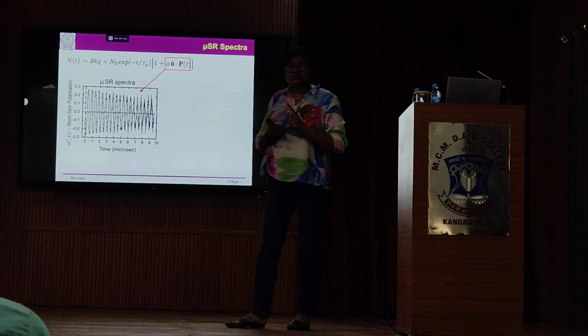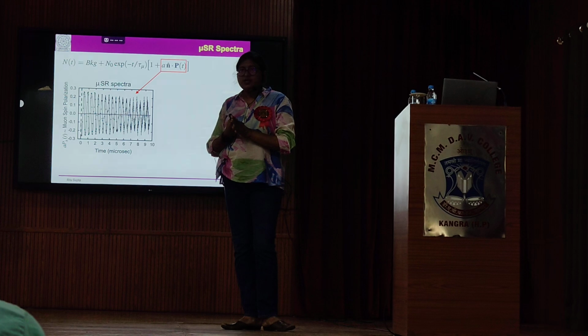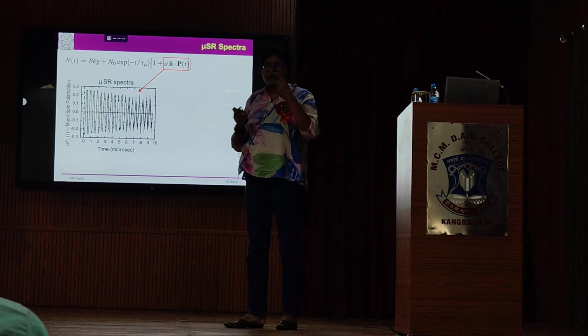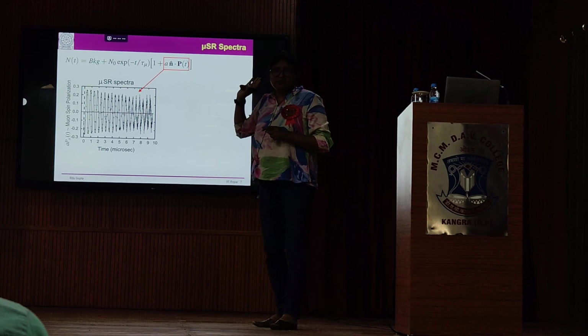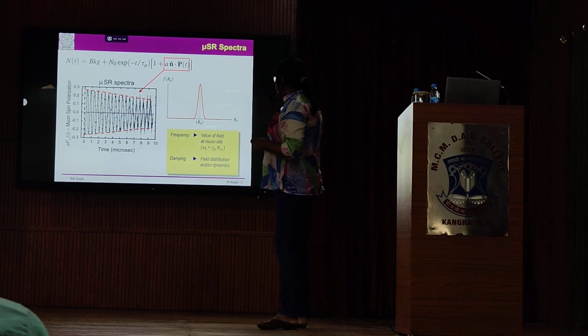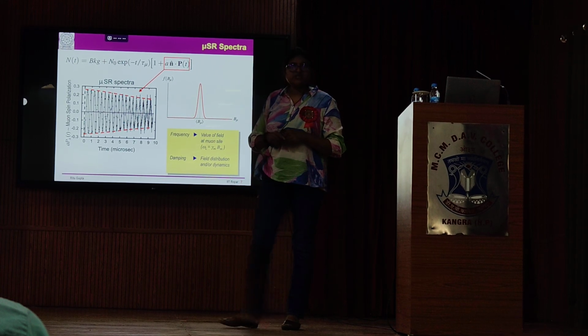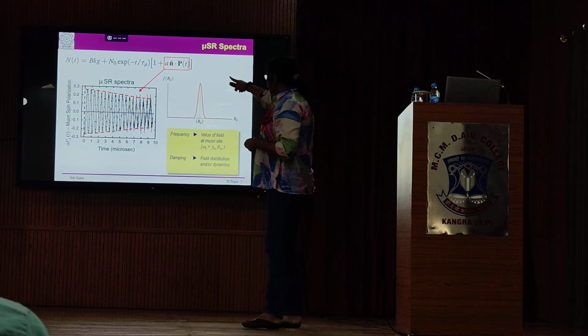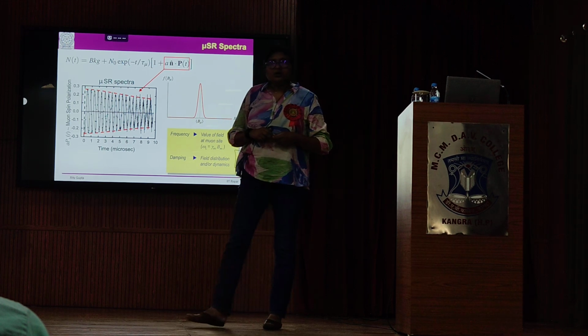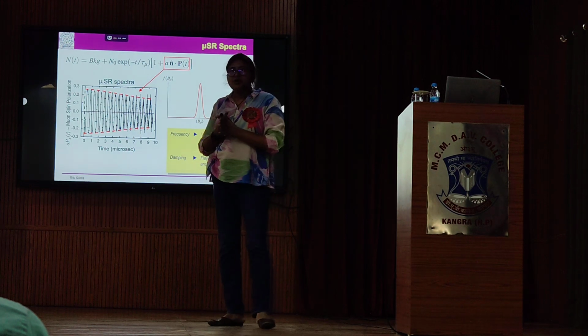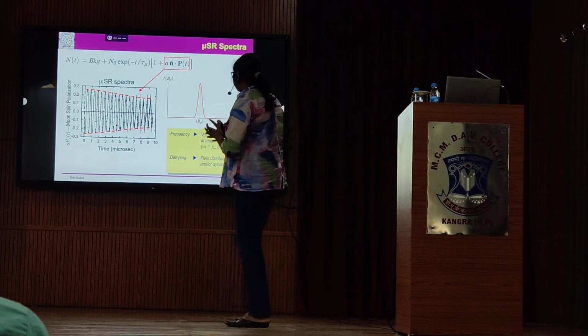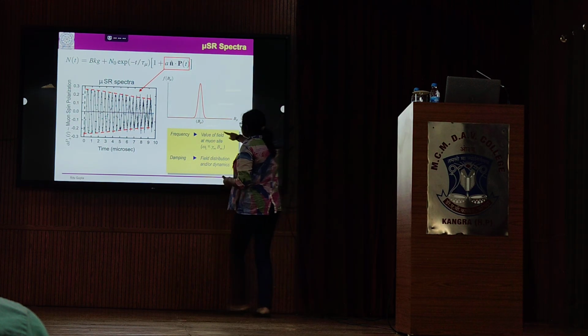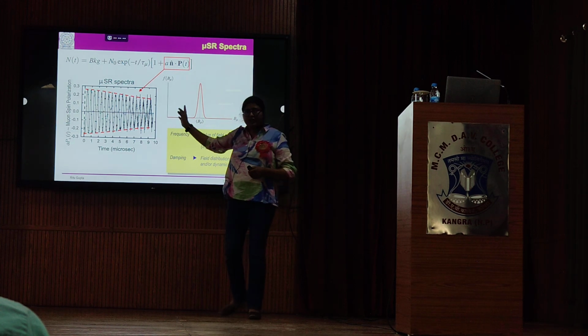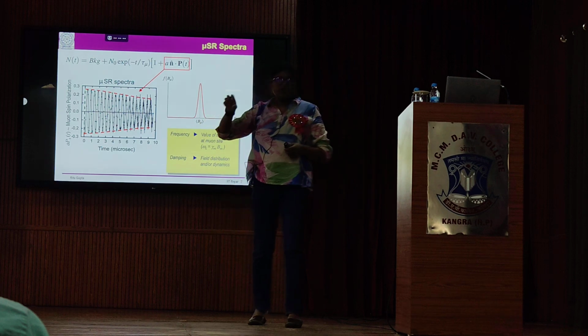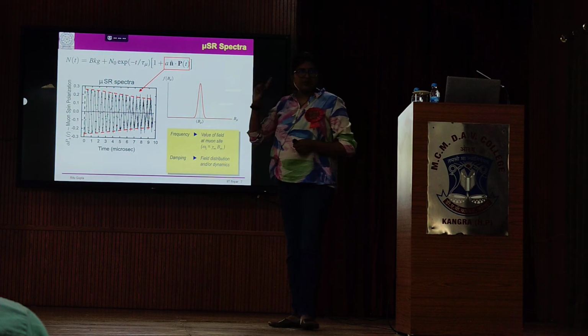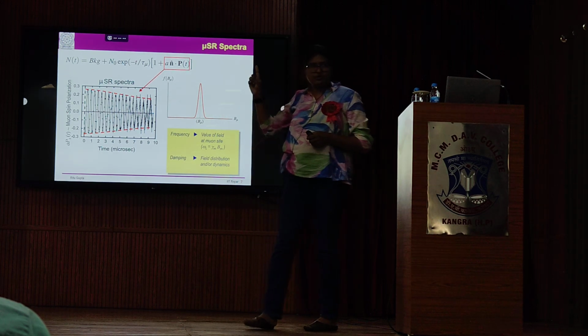So why are there oscillations? Because you apply a magnetic field from outside. Okay, so then the muon spin precesses around that magnetic field, and the oscillation frequency is giving you the magnetic field. Okay, so the frequency will give you the value of the field which is experienced by the muon, and the decay of that signal will provide you information about the field distribution. For example, if you have a normal material and you take the Fourier transform of this spectra, there is no field distribution, so you apply a magnetic field from outside and you will see a single peak. Whatever the field you are applying, you will see a peak corresponding to that only.